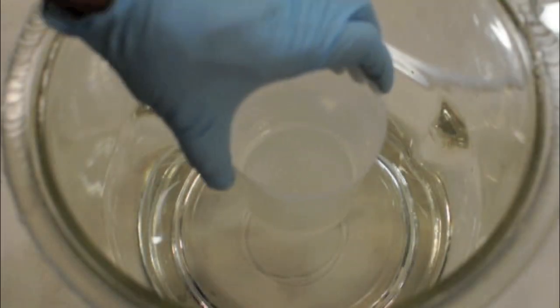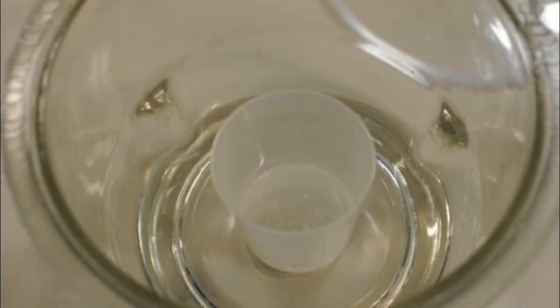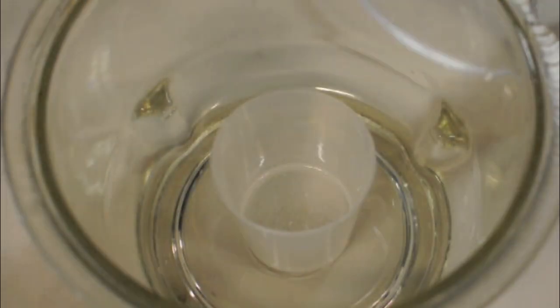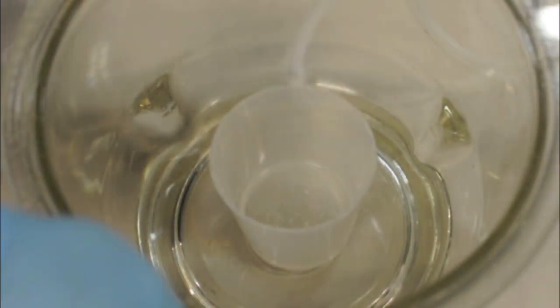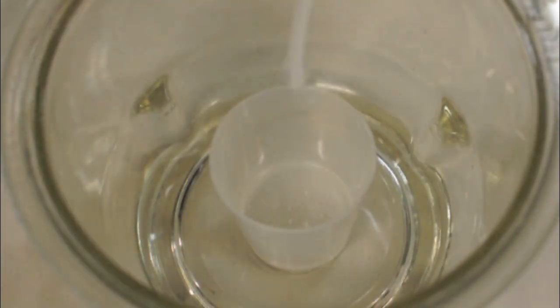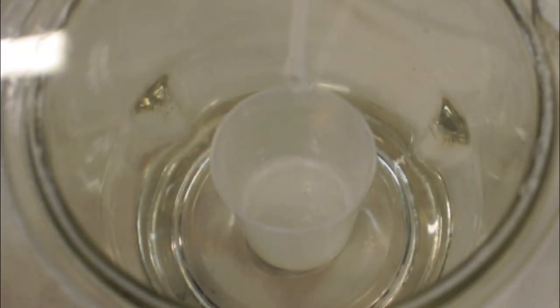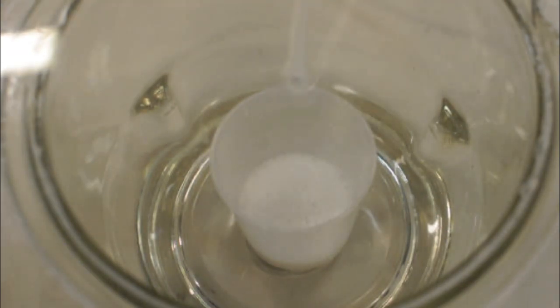When degassing resin by this method, always be sure to use a container that is much larger than the amount of resin you wish to degas. Under vacuum, the air in the resin will expand, causing the resin to foam. This is why you want to always use a container that's much larger than the amount of resin you are trying to degas.